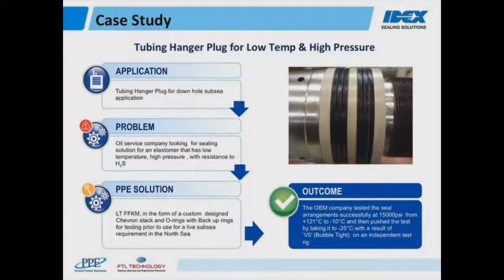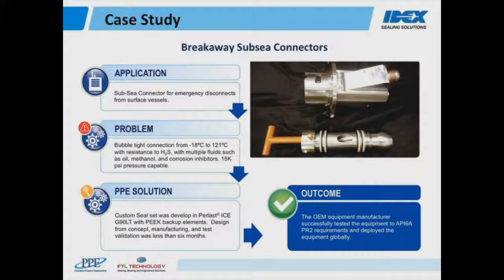This case study is for breakaway subsea connectors. The application is a subsea connector that would disconnect in emergencies from surface vessels. Now the problem was getting a bubble tight connection from minus 18 degrees C to 121 degrees C with resistance to H2S in multiple fluids such as oil, methanol, and corrosion inhibitors, and be 15,000 psi pressure capable.